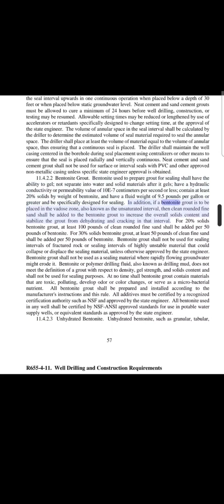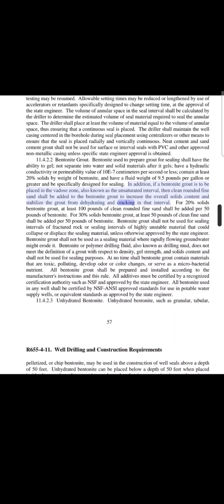In addition, if a bentonite grout is to be placed in the vadose zone, also known as the unsaturated interval, then clean rounded fine sand shall be added to the bentonite grout to increase the overall solids content and stabilize the grout from dehydrating and cracking in that interval. For 20% solids bentonite grout, at least 100 pounds of clean rounded fine sand shall be added per 50 pounds of bentonite. For 30% solids bentonite grout, at least 50 pounds of clean fine sand shall be added per 50 pounds of bentonite.